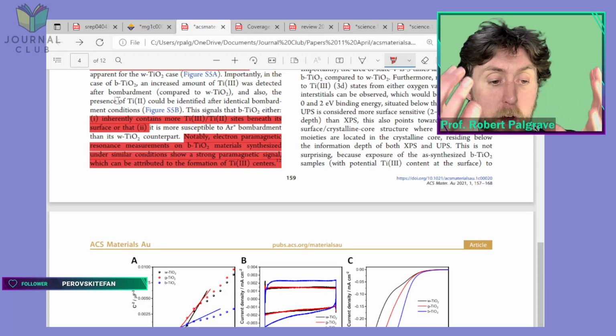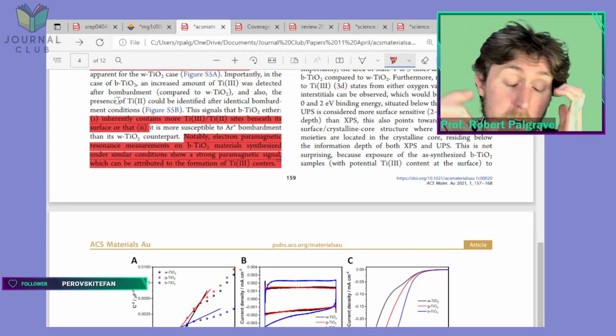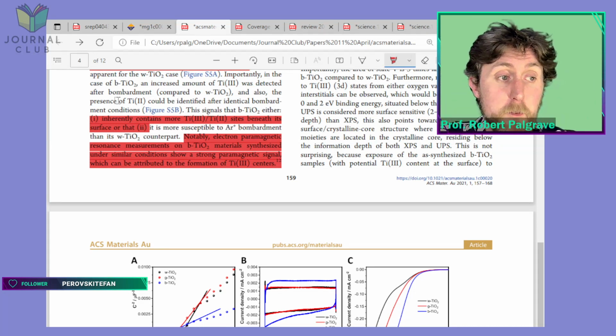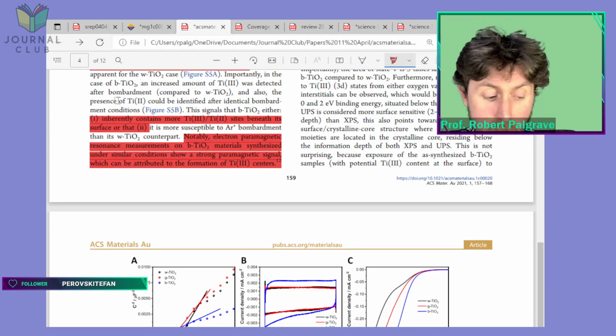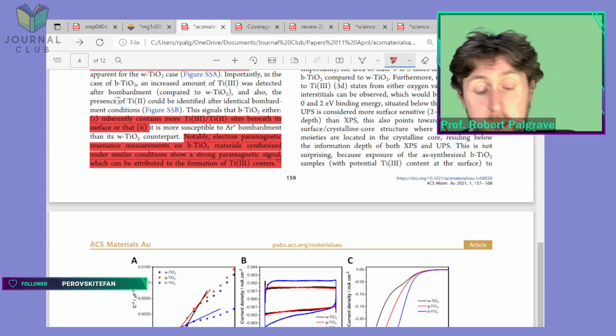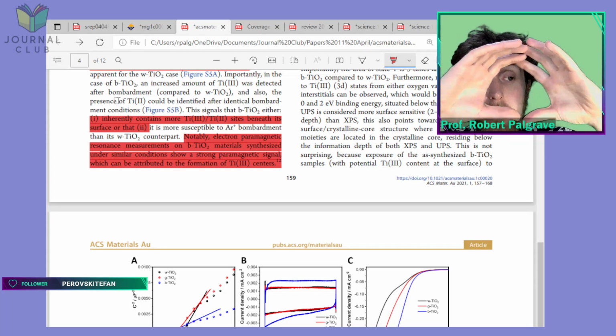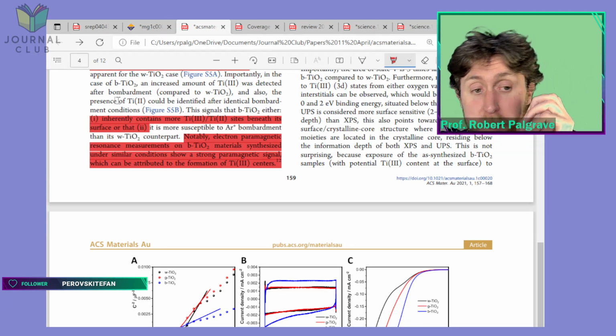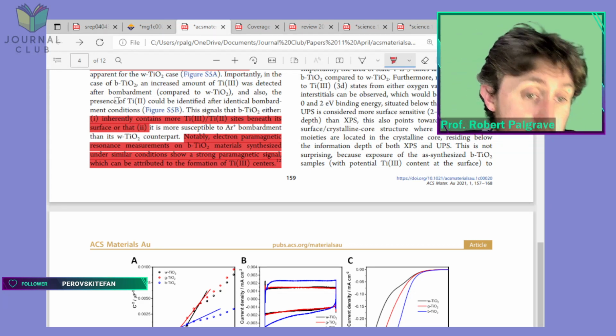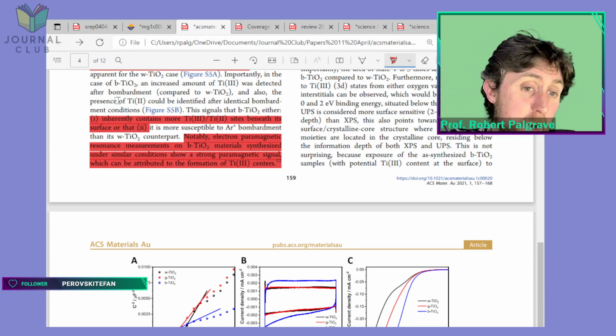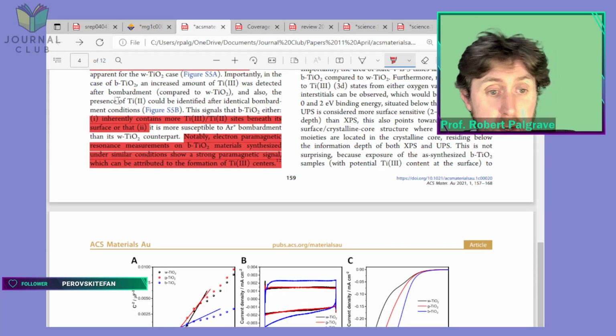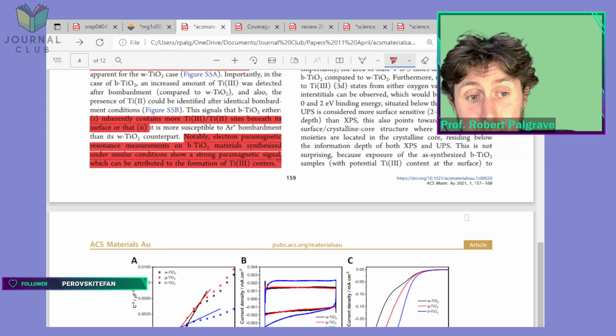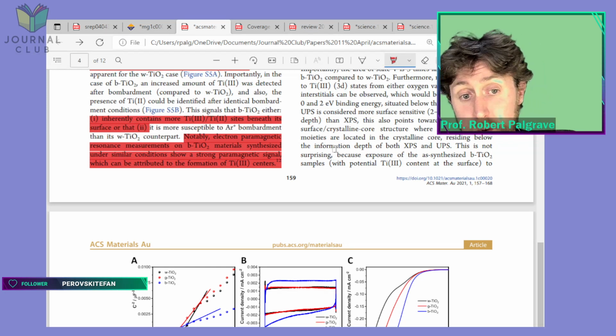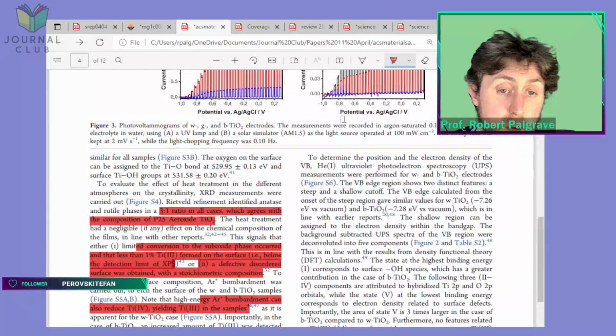Now remember, we're talking about a particle which is only 25 nanometers in size, so the outer 5 nanometers of that is quite a large proportion of the nanoparticle volume. You're looking at quite a large part of the nanoparticle with XPS. So the idea that underneath there's an oxidized layer, and then somewhere deep inside the nanoparticle there's some Ti3+, which is only revealed by argon sputtering, would require it to be quite far inside, because otherwise you'd be able to detect it with XPS. So it's still a little bit puzzling: is there Ti3+ here after hydrogen doping, or is it only generated by the argon ion bombardment?